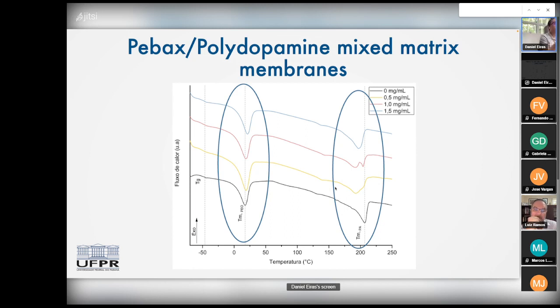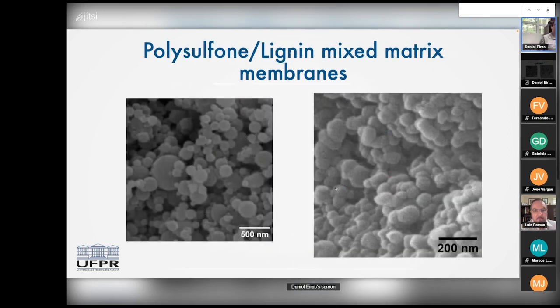I'm using these results just to illustrate the kind of work that we do here. When you modify the polymer, there are certain interactions that are difficult to expect, and that influence the polymer. So we were expecting just to increase the solubility selectivity, but we ended up increasing the diffusion selectivity by reducing the diffusion coefficient. That resulted in a decrease of the permeability.